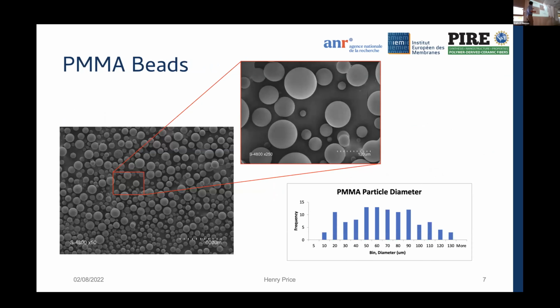Now, a bit on the PMMA beads I used. These were micro beads. I did some image analysis of some SEM images to get an idea of the ranges of the diameters of these particles. You can see it's a pretty wide spread, but it centers around 60 to 70 microns in diameter. This would affect the pore size after pyrolysis, so we're working on a scale of micro pores.